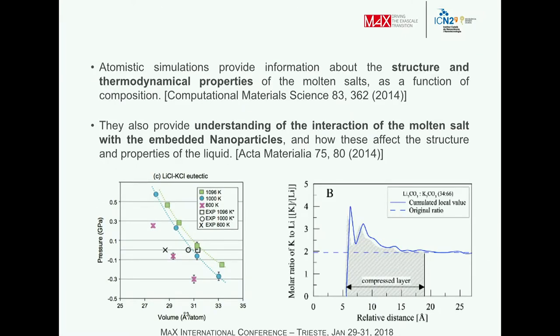These are papers that appear also in the same year, so they were computing the thermodynamic properties of the molten salts, like the PV curves, or the effect of the inclusion of nanoparticles in the molten salts. This was a silicon nanoparticle, and they saw that the structure of the liquid in the border, in the surface of the nanoparticle, which goes up to here, is quite dramatically affected. So there is some layering, some compressed layer that they claim is the origin of this increase in the thermal